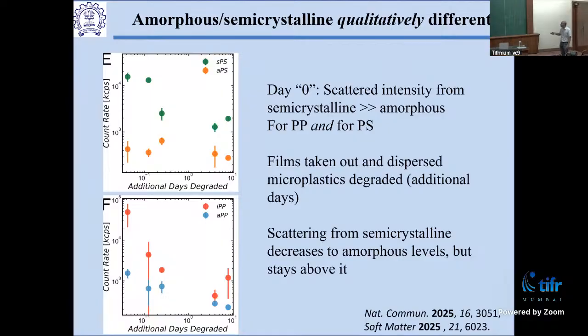I'm going to just tell you what happens on day 0. The scattered intensity from the crystalline polymers is much greater than what you see from the amorphous polymers, right? But then you take these out and then continue to degrade them. I'll come back and talk to you about this later. And what you see is that if you continue to degrade them, the amorphous polymers, the scattering from them comes down even further to almost the level of what you see from water.